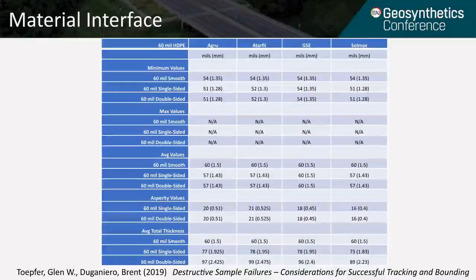This table is here to show the difference between textured and smooth interfaces. If you look at the bottom of the table, you can see that if you were welding two sheets of 60 mil smooth together, you're roughly going to be at 120 mils that you're welding between the rollers. When you get to the double-sided, you could be close to 200 mils of total thickness. When you're using these different thicknesses, obviously that's going to mean different heats required for the weld, different speed, and ultimately different pressure as well. And the installer needs to be making those adjustments if they're going to get a good weld in the field